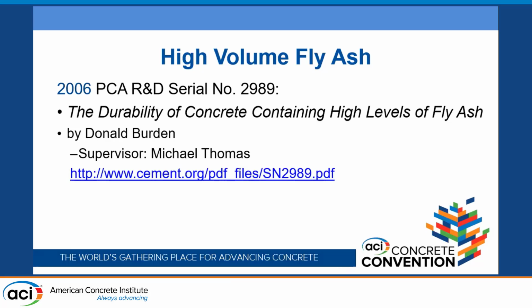Michael loves SCMs, as most of you know, and we all are pro using products to the right volume. And I think Jason summarized it perfectly. It can make good concrete better, but if you're using it in the wrong amounts, it can make bad concrete worse. So this research presented laboratory data on the effect of curing and carbonation and permeability rates of high volume fly ashes. And the data did indicate that high volume fly ash carbonates significantly faster than plain Portland cement concretes at the same water cementitious materials ratio.